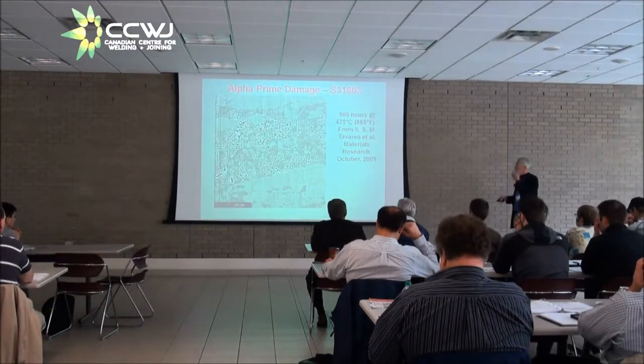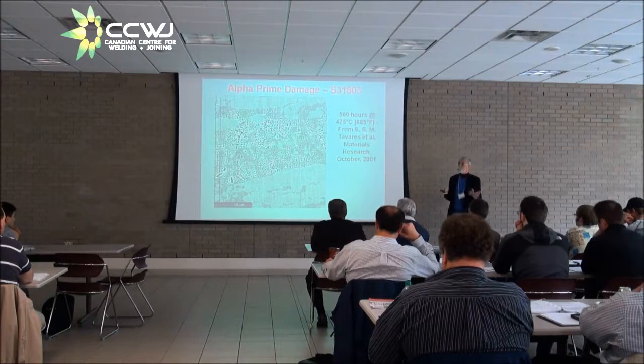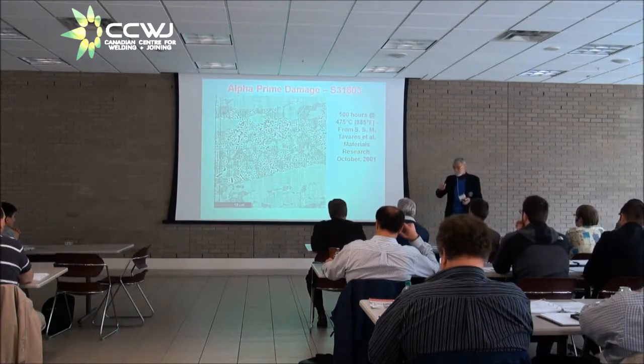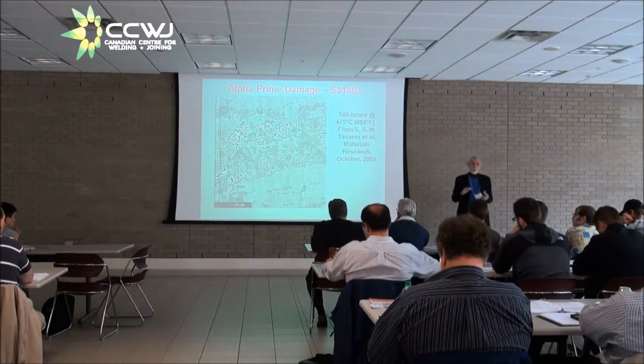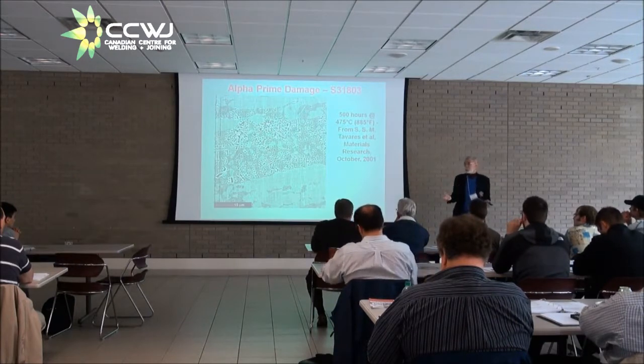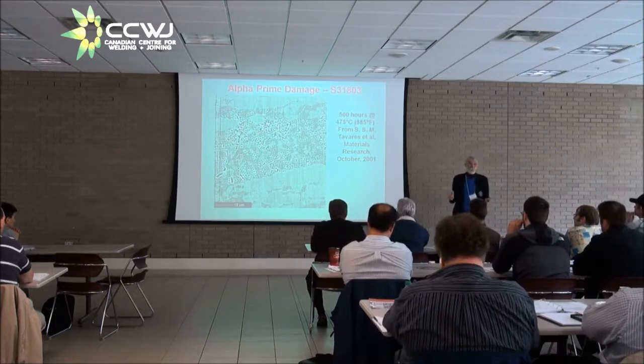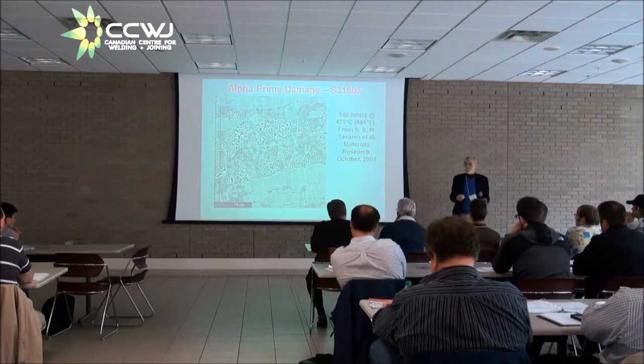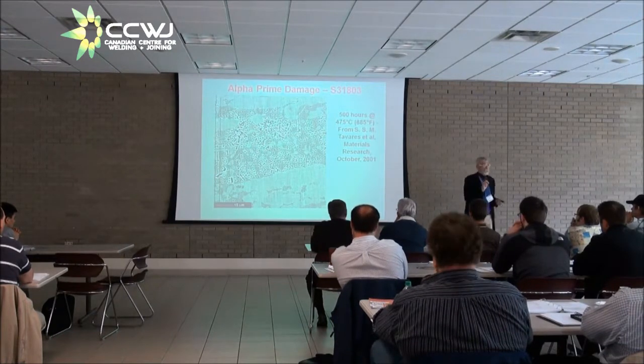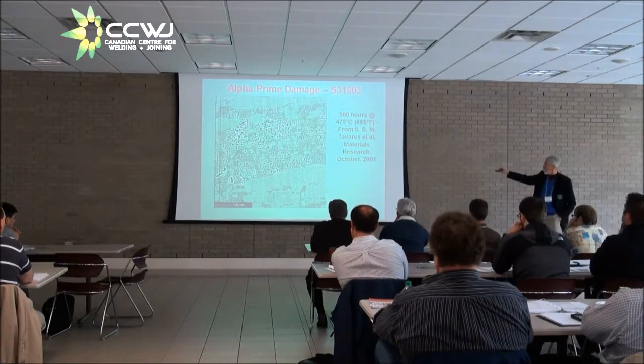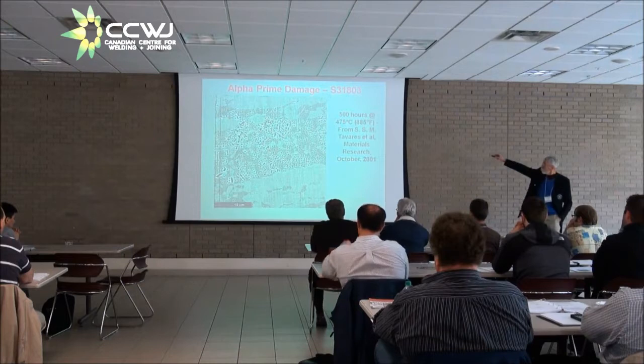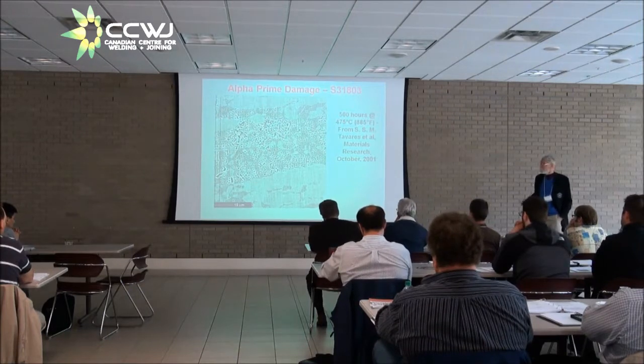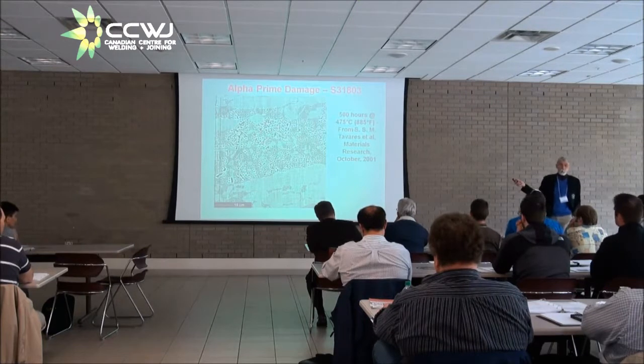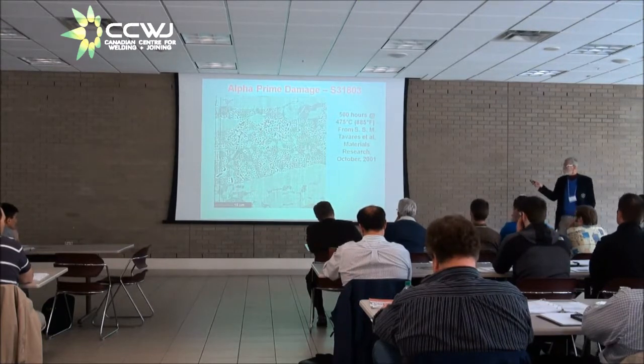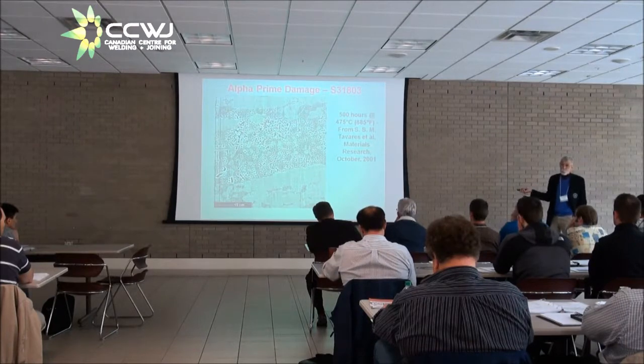And if you look at corrosion, what was done here was to use an electrochemical pitting cell to just increase the potential until you got the first surge of current in the electrochemical cell. And that's the initiation of pitting. Then you stop the process immediately. So instead of getting big pits that you can stick your finger into or stick a ballpoint pen into or something like that, you get little bitty pits. And you can see here, all the pits are in the dark etching material, which is the ferrite. There are no pits whatsoever in the austenite. You can't see the alpha prime. You need a scanning transmission electron microscope to see that. But you can see the pits that result from the chromium depletion next to the alpha prime condition. So that's very destructive to the properties of the material.